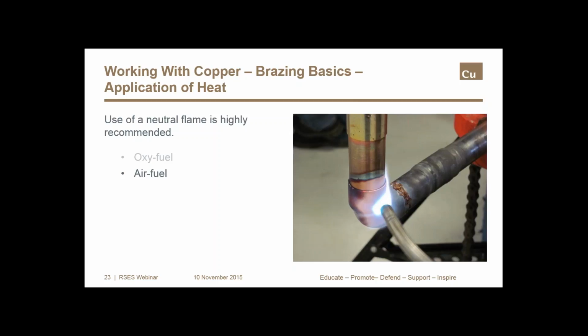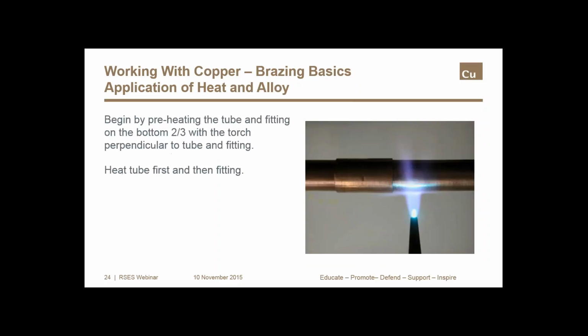Air fuel is sometimes used on smaller joints. Remember, again, to use a neutral flame. The tube should be heated first, beginning about 1 inch from the edge of the fitting and sweeping the flame across the tube in short strokes. The flame should be at right angles to the tube. It's really important that the flame be in motion and not remain on any one point for too long. Even though copper melts at high temperatures, nearly twice the melting point of aluminum, for example, too much heat in one spot for too long can be enough to damage the tube.